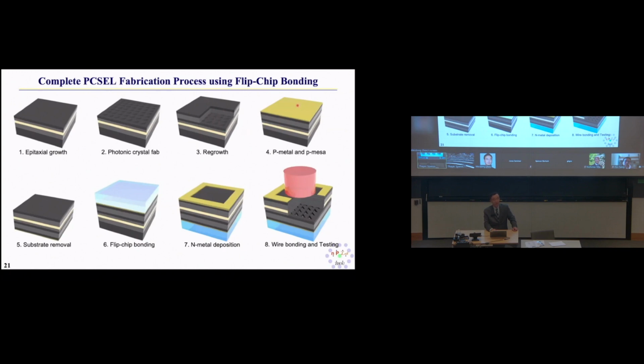Then we put the electrode on. That's the P metal, for example, and form the mesa. Then we flip it over to bond onto the heat sink substrate. You can remove the substrate, bond on the diamond, and flip it over. Then we put another contact on the substrate side, in this case, the ring contact. So light will come out from the substrate side. So basically, put it back upside down.